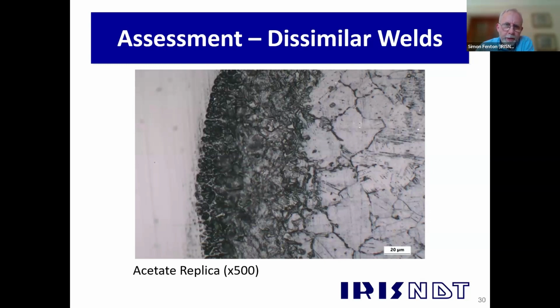But this does illustrate what Pete was saying earlier, in that there is a limitation to replicas. Next slide, please, Pete, which is the same photograph. The possibilities here are really that we've got an etch effect because of the dissimilar materials causing this light etch, this dark etch, or we could have a region of carbon migration. But even using the PMI techniques, the X-ray fluorescence detectors that we can take to site, we're not able to investigate the carbon content across that heat affected zone. So really the only way to solve this issue is to have a real sample of material back in something like a scanning electron microscope.